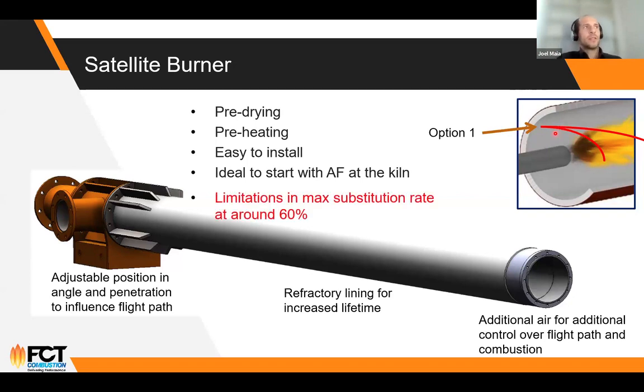However, there's a drawback. Obviously, this is not the main burner. So when you look inside the kiln, the majority of the fuel should be in the center of the kiln, and now you are injecting alternative fuel on the top of it. So you have a limitation about the substitution rate that you can have through this pipe itself. We have seen cases at a maximum of around 60%, but mostly these are in the range of 30, 40, 45%. As I mentioned, the majority of the fuel should still be at the main flame coming from the main burner. So when you start shifting too much energy to the satellite burner, you are injecting more fuel through a burner that is not as capable as the main burner itself. So it starts making not much sense.